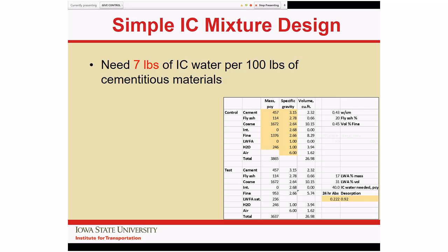Some of the work by NIST and some of the exotic chemistry and number crunching and modeling basically comes down to a pretty simple answer. We need about 7 pounds of internally provided internal curing water for every 100 pounds of cementitious materials in the mixture. It's a pretty simple spreadsheet, and I can send this to anybody who needs it. Otherwise, Jason Weiss has a spreadsheet, and the Expanded Shale and Clay Institute has a spreadsheet.